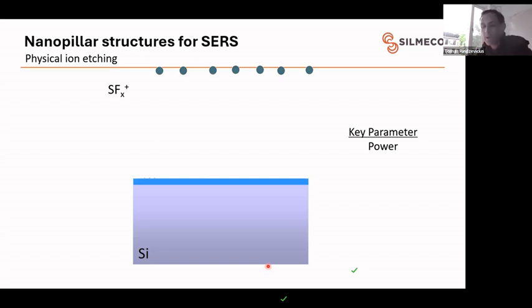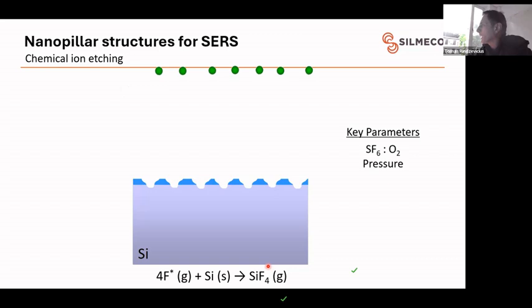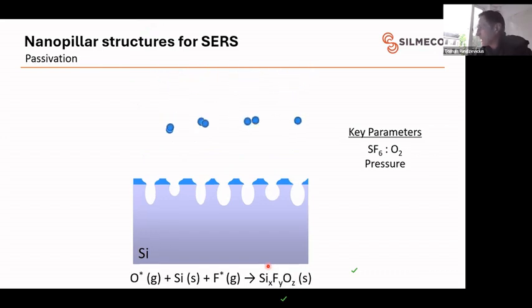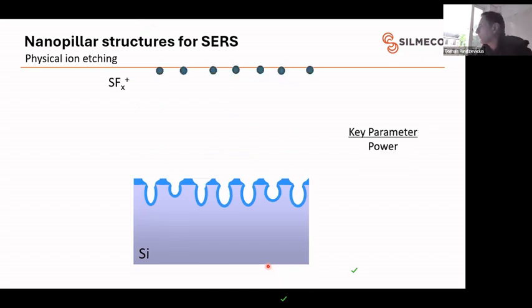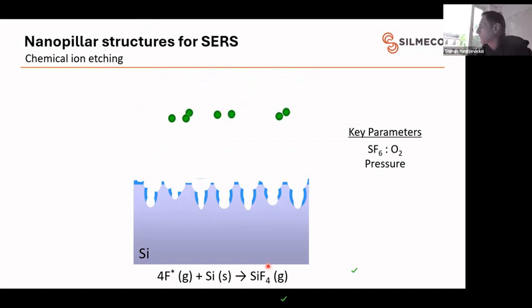When you insert a clean silicon wafer into a chamber, the reactive ion etching starts with basically physical ion etching, because you need to cut through the oxide layer on the silicon that typically is very thin. Then the next step, you have a chemical etching. Now the SF6 basically starts to etch silicon chemically. But at the same time, you also have some portion of oxygen that creates a passivation layer, so that you don't over etch. And then you basically repeat these steps, one after the other, and you create this kind of corrugation.